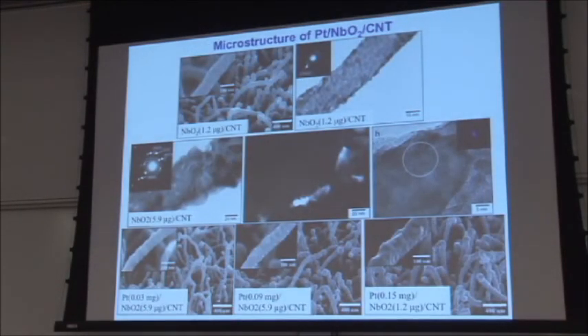So when we grew the niobium oxide on the carbon nanotubes, the structure was fundamentally different. Niobium oxide wets carbon nanotubes quite well. So this is the thin and the thicker. This is the 0.2 nanometer. This is the 1 nanometer layer of niobium oxide on the carbon nanotubes. You're seeing, these grains really resemble pancakes wrapped around, let's say, a drinking straw, around a water hose.